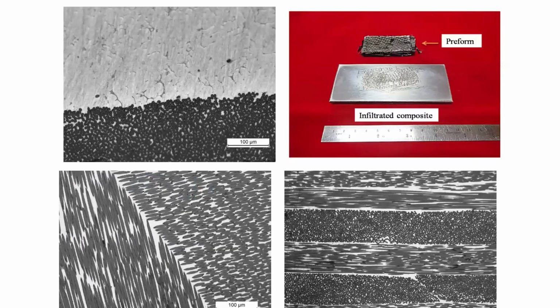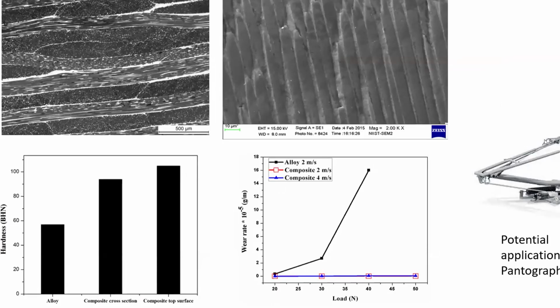Similarly, we also used carbon fiber. I'll not go into very much detail; I will just quickly skip on because the time is already over. Again, we used these fibers infiltrated with liquid metals. Because of the self-lubricating behavior, this can be used in pantographs. Self-lubricating means it will not wear. There will be a lubrication layer which forms. So the alloy wears very quickly, but the composite does not wear quickly, because of the formation of the lubrication layer from the carbon fiber at the interface.